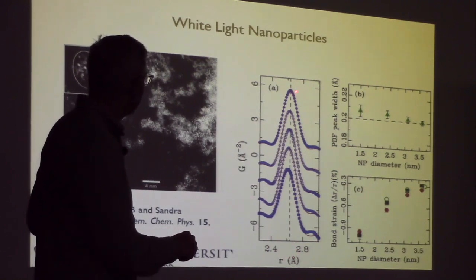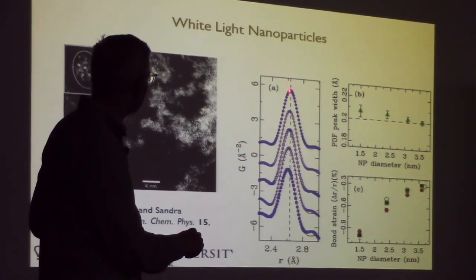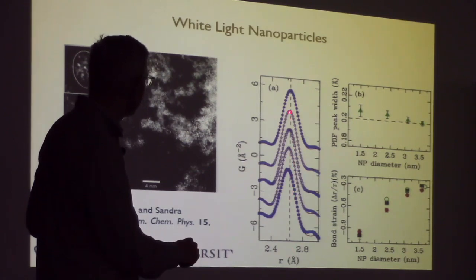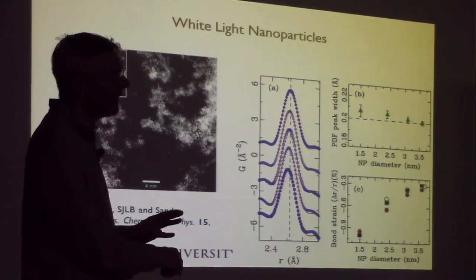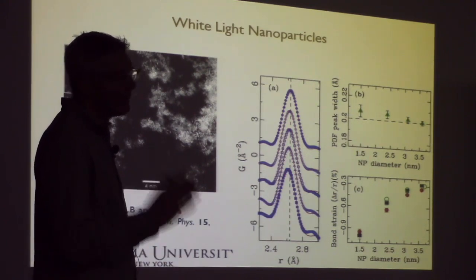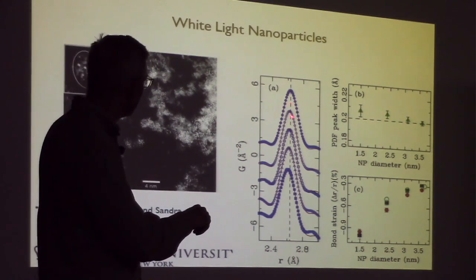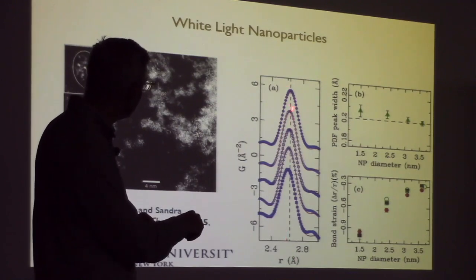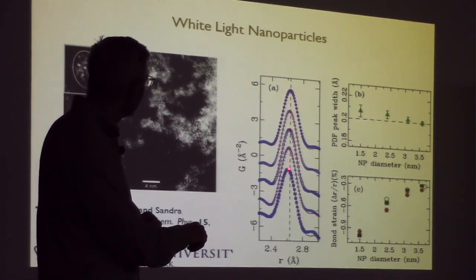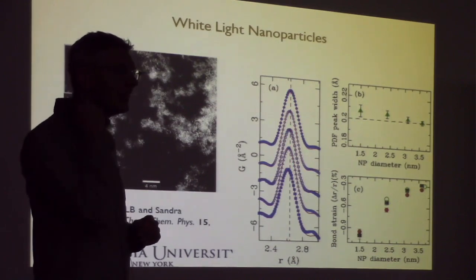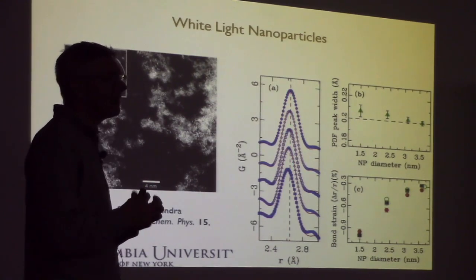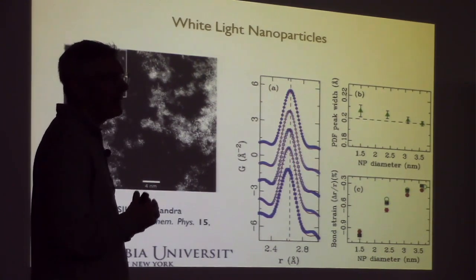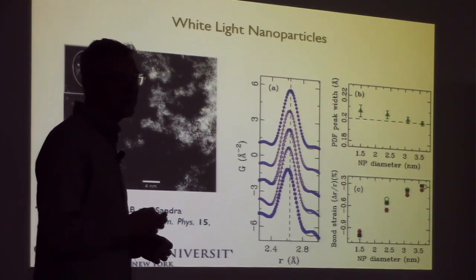And it's this distance here, and this is the bulk material, and this dashed line is through the center of it. And if you look very carefully, this is the 4, 3, 2, and I've added another data set, which is 1.5 nanometer diameter nanoparticles. So the nanoparticles are getting smaller as we go down, and what you see is that this cadmium-selenium bond shifts to the left, shortens. So there's a compressive strain, size-dependent compressive strain in these nanoparticles.